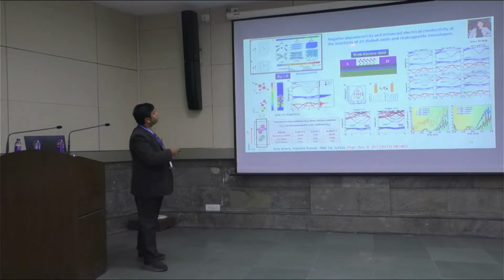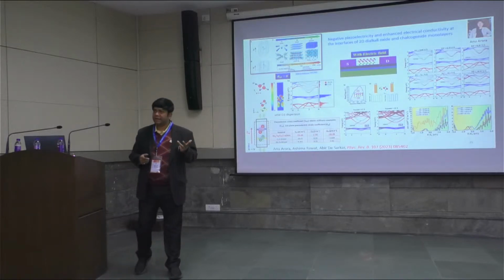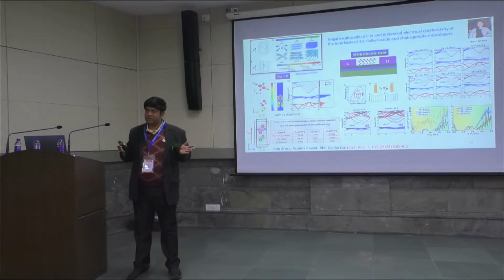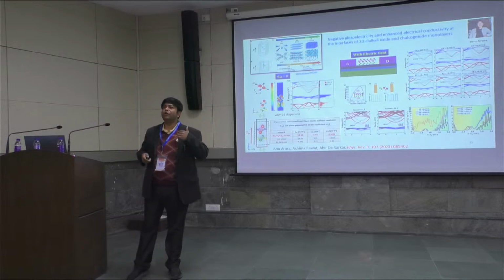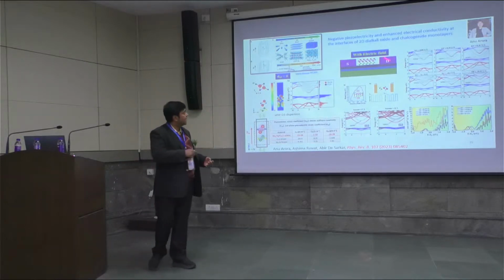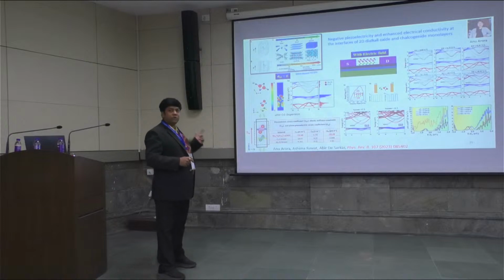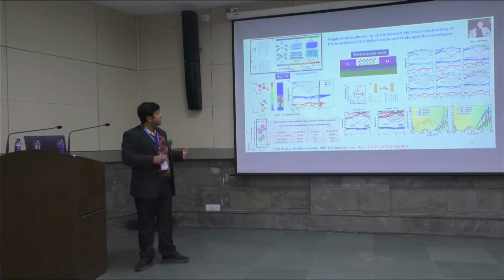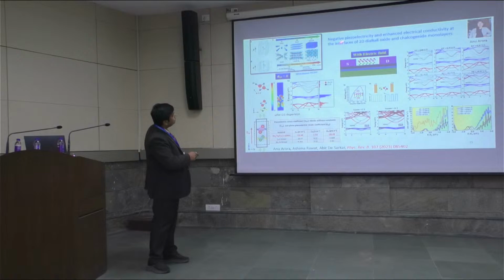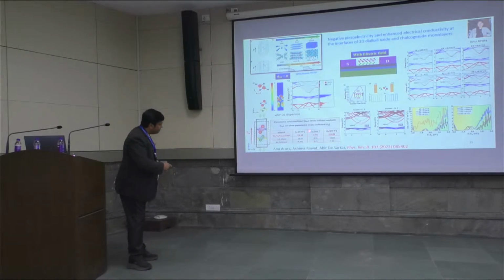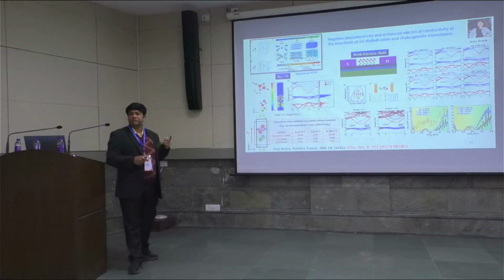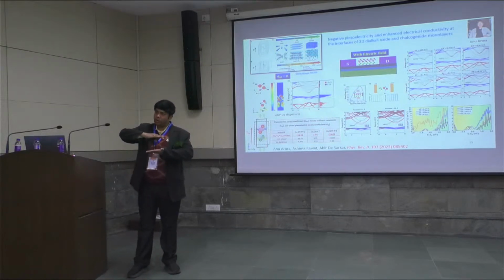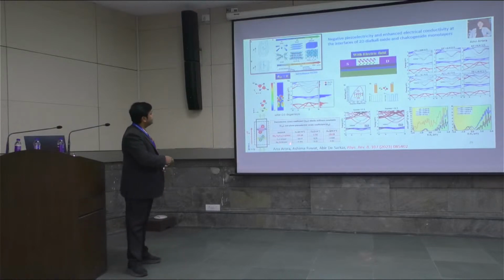So now we usually calculate the piezoelectric coefficients. Experimentally, we measure the piezoelectric coefficients, but we usually ignore the sign of the piezoelectric coefficients. The sign can be important even from fundamental perspectives. So we have ascertained the origin of the negative piezoelectric coefficient. We find that it arises from a small out of plane elastic stiffness constant. In van der Waals heterobilayers, you have a small out of plane elastic stiffness constant, so that gives rise to a negative out of plane piezoelectricity. That is what we find over here.